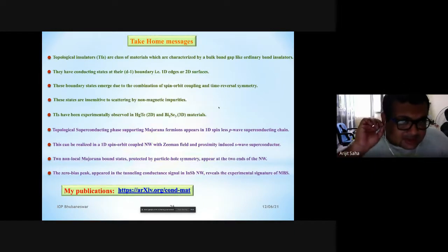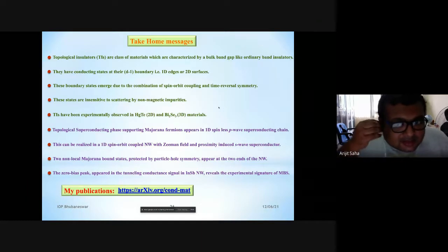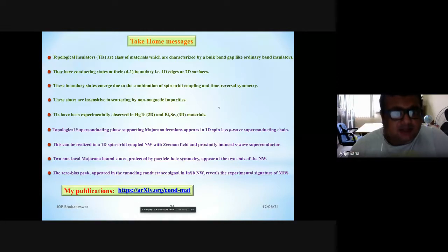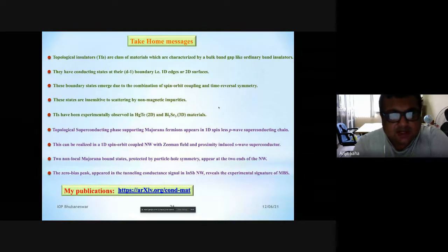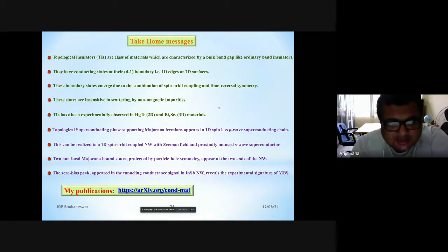So at the end, what is your take-home message? Topological insulators are a class of materials which are characterized by a bulk bandgap, like an ordinary insulator, but they have conducting states at their d-1 boundary. So if I choose d equal to 2, then I will have a 1D edge mode, and if I choose d equal to 3, I have a 2D surface. This boundary state emerges as time reversal Kramers pairs due to time reversal symmetry, which comes due to the presence of spin orbit coupling, which preserves time reversal symmetry, unlike the magnetic field in the quantum Hall case.